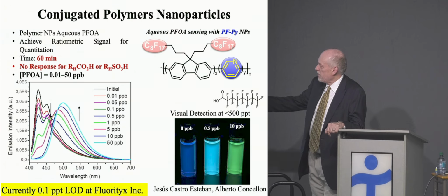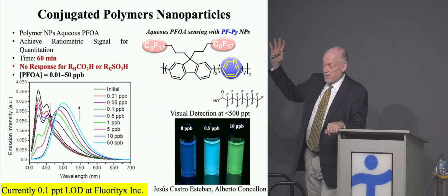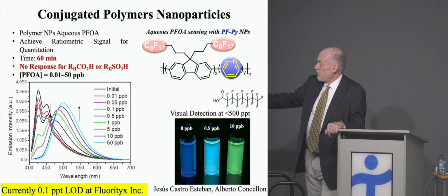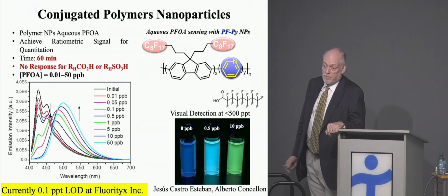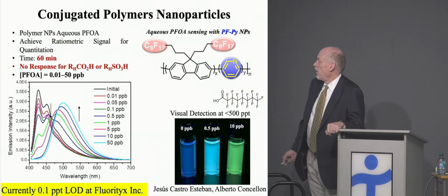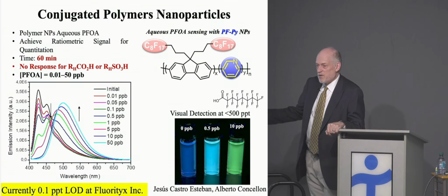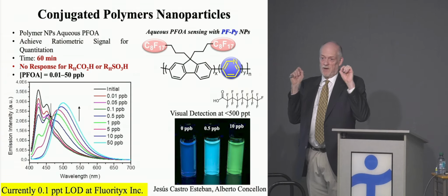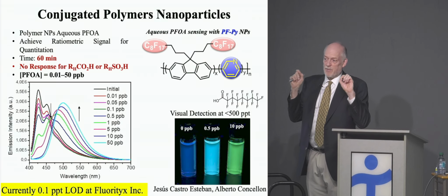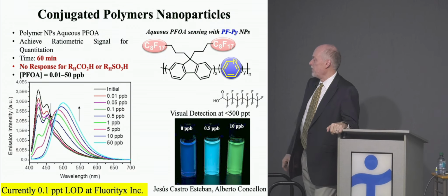And so here, without PFAS, this is blue. This is just the fluorescence, or the emitted light that comes out of this. It looks like it's glowing blue, right? And at very low concentration. And then as you increase the PFAS in this water, it turns to green, and here's somewhere in between. So here you're seeing that we can see 500 parts per trillion detection just with your eyeball. And the fact we have these two signals means we can use the ratio of them, and it actually gives you internal quantitation. So this is something that you can get quantitative data out of.